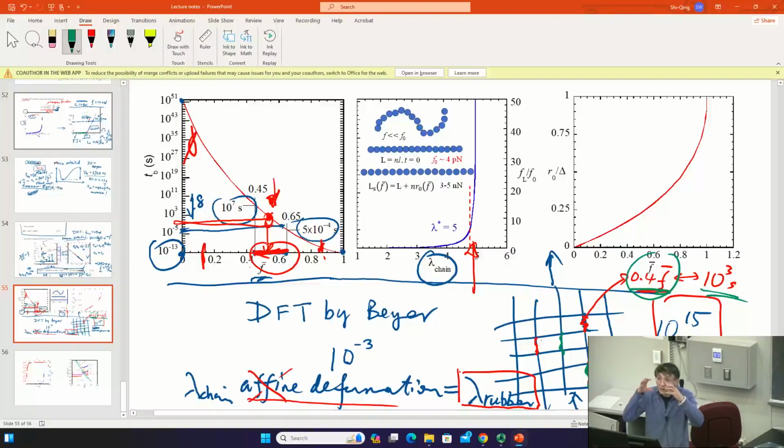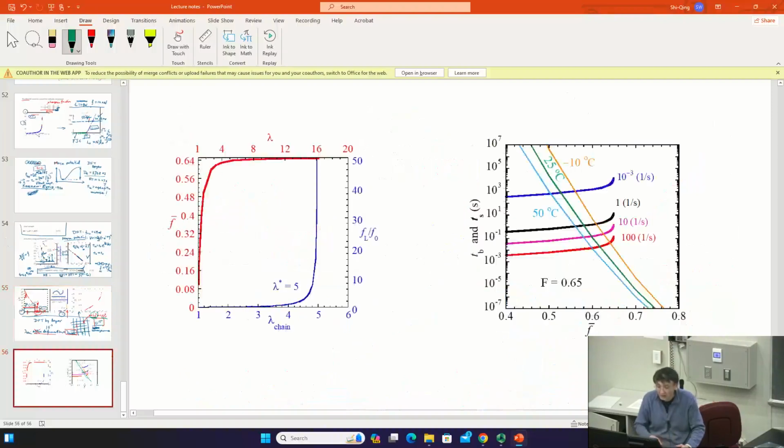Okay? So I'm suggesting that I have to think about a population of chains gathering enough tension in them, and then they march on to higher tension and lower lifetime. A mouthful, what I said is to be captured by this red curve. This is untested, but I conjectured it to capture what I said. It will, no matter how you are growing your stretching, this is microscopic stretching, the rubber one.